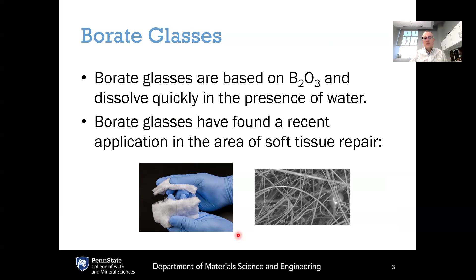However, recently Delbert Day and his company Mo-Sci have developed borate glass fibers that have been used for soft tissue repair. In diabetic patients who have deep ulcers that don't heal on their own, these borate glass fibers can be stuffed into the wound, and their fibrous microstructure provides a natural pathway to stimulate the body's healing process. The glass dissolves on a timescale of a few days, delivering chemicals the body needs to heal, and the borate component is antimicrobial, helping prevent infections.